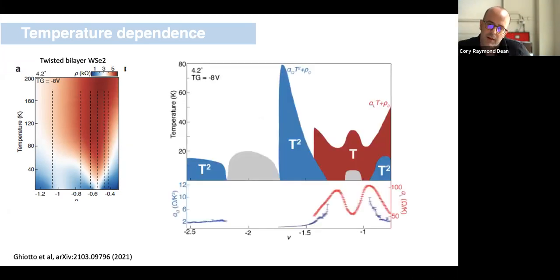Okay, so here's just a summary cartoon diagram of what we see. This gray curve here is identifying where we have the half band insulator. This gray region here is identifying where we have the full band filling, where we see something that's more insulating-like. And over this temperature range and density range, what we see is that around the half band insulator, we seem to see a fairly wide range of doping where we see something that really is T-linear behavior. So in correlated systems like cuprates and heavy fermion systems, et cetera, this is what might be identified as a strange metal. So in this system, I want to be a little bit careful. There can be a lot of heated debate when you bring up the notion of a strange metal.